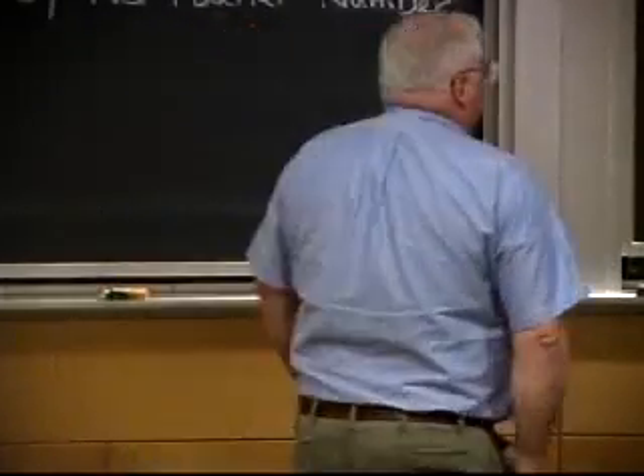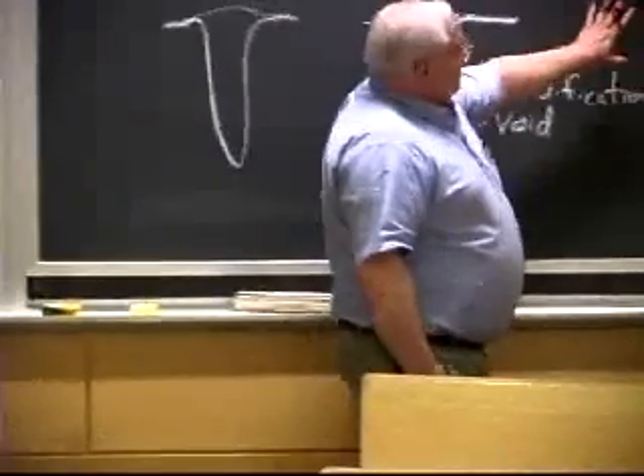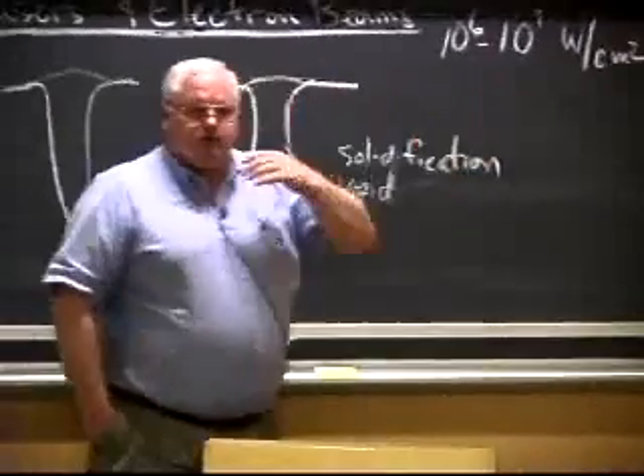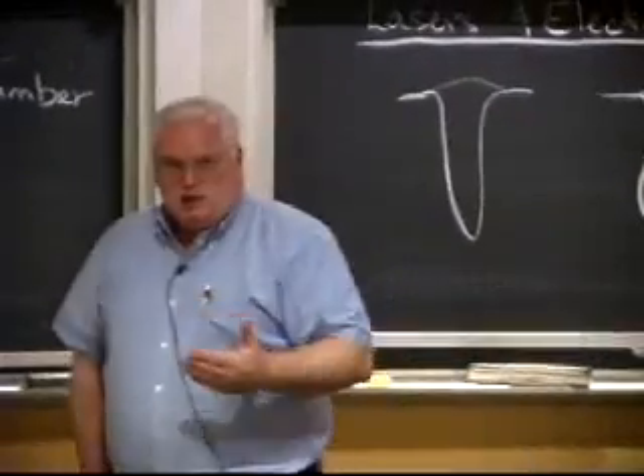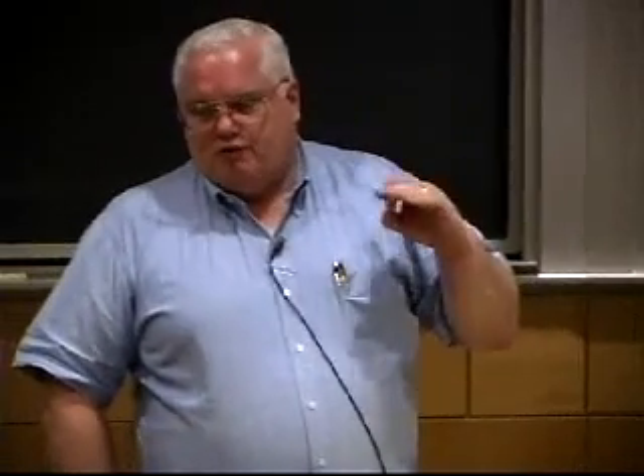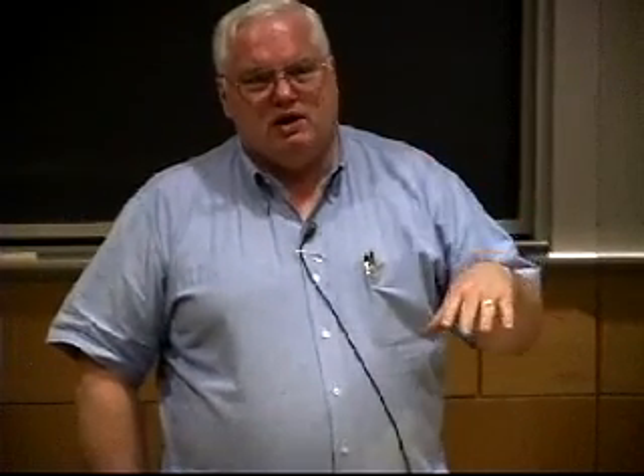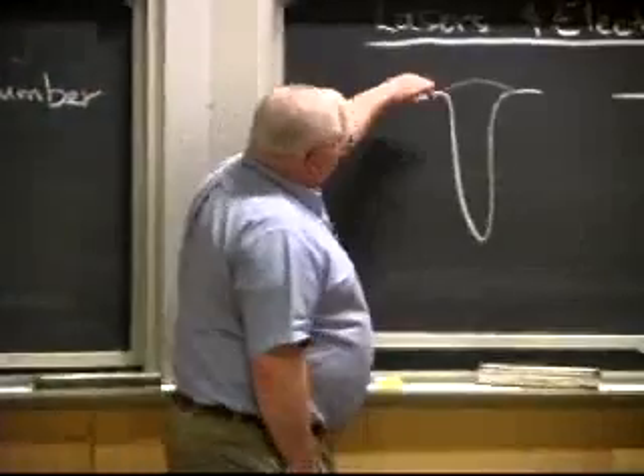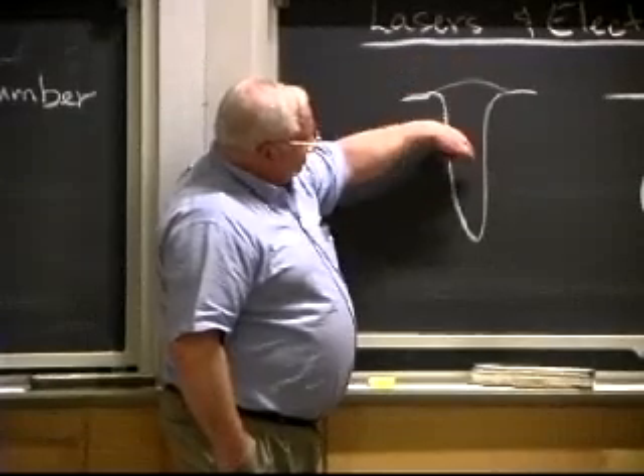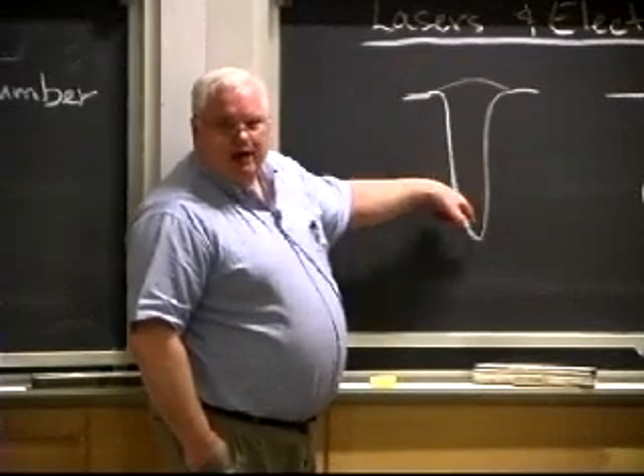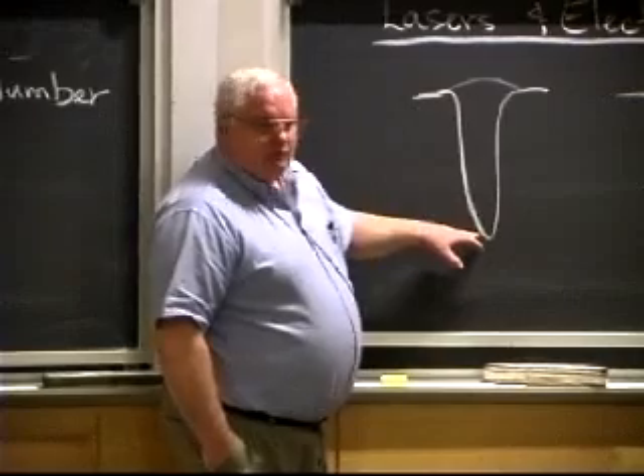So today I wanted to go over, we've been pushing out from flames and arcs, laser and electron beams, which are at the far end of the heat intensity spectrum, 10 to the 6th to 10 to the 7th watts per square centimeter. Turns out, as we said before, if you go above 10 to the 7th watts per square centimeter, you just start drilling holes. The material cannot carry the heat away fast enough. And if you do this, before you get to the point where you're drilling holes, you can actually have a deep penetration weld and a high depth to width ratio.